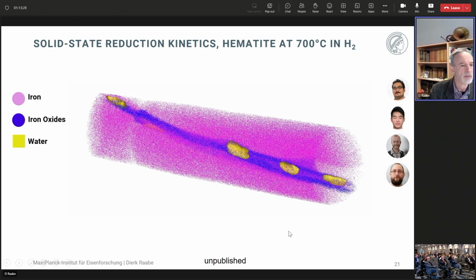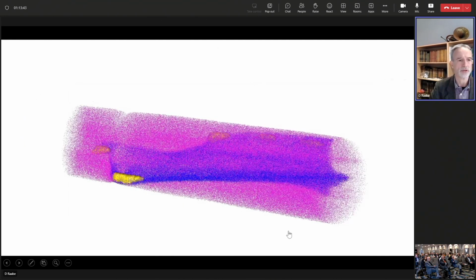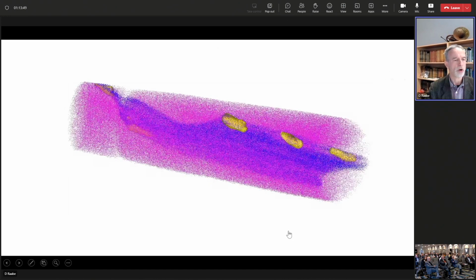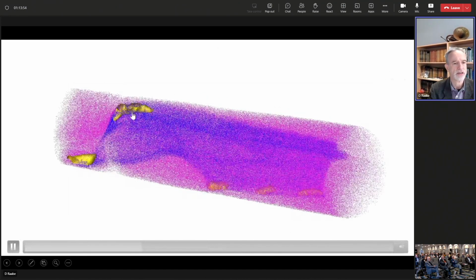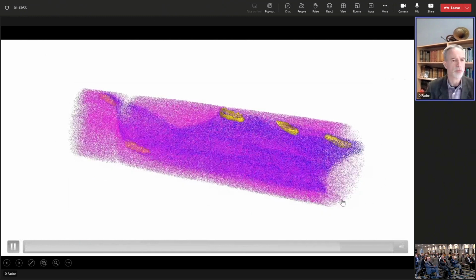And what happens then, let me move to the little movie. I hope you can see it. You can see these pink-colored atoms. This is the pure reduced iron, measured now at atomic scale. Then you see in the center of that sandwich the remaining wüstite layer, so the unreduced material. And you can see on the rims of this sandwich, colored here in yellow, the water content. And that is something which we try to understand and image by cryogenic atom probe tomography.